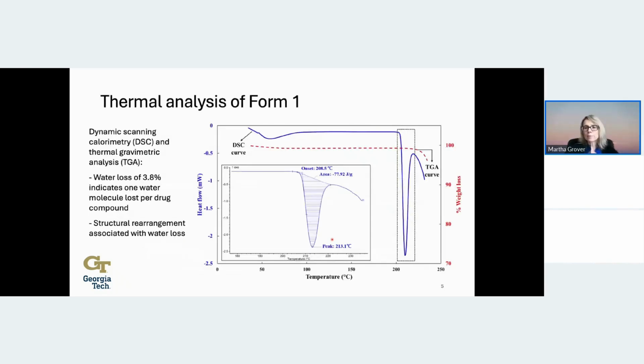So before we got into actually crystallizing the pharmaceutical compound, we wanted to characterize the monohydrate, form 1, that we had received from BMS. And so we used differential scanning calorimetry together with thermogravimetric analysis. And on the left here, we have the heat flow from the DSC. And then on the right, we have the weight loss from the TGA. But these measurements are being made simultaneously under a dry nitrogen flow.